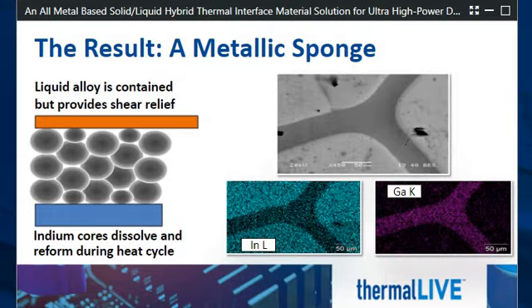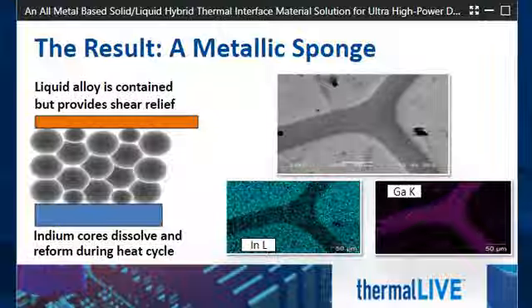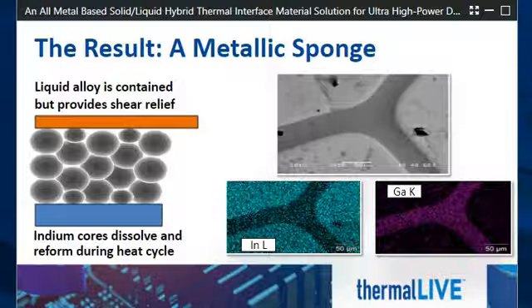And on this slide, we can see how indium will react with gallium-based liquid metal alloy. Gallium will go through the grain boundaries of indium, providing wetting on the surfaces of the solid solder preform. Thanks to the solid indium preform, the newly formed matrix will have high thermal conductivity, and liquid metal will provide low interface resistance. The solid indium preform will also help keep liquid metal in place, so none of the material could be squeezed out.